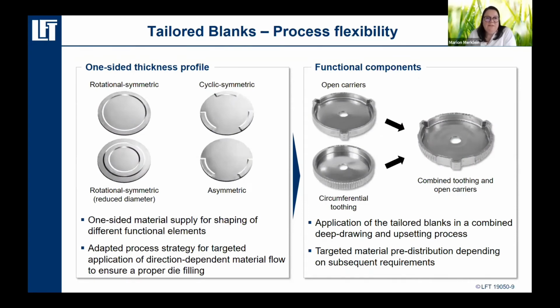After our first success, we were interested in seeing which geometries we can realize. And so we started, as you can see on the left, with a rotational symmetric geometry. That was the real beginning. We had a thickening at the outside. Then we said, okay, let's have also a rotational symmetric geometry on the inside with a reduced diameter. And of course, then we had the idea, oh, there must also be the possibility to realize cyclic symmetric and asymmetric geometry. And as you can see, this is also possible always in the same machine using only different tools. And of course, this will open different possibilities to realize different geometries.